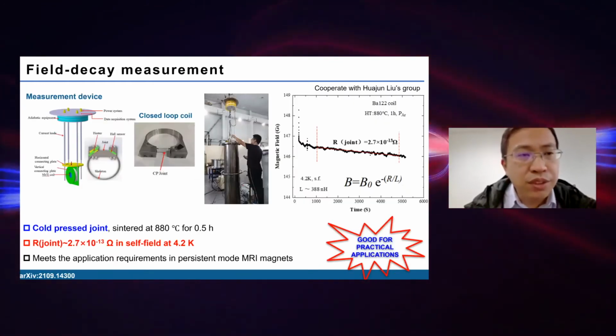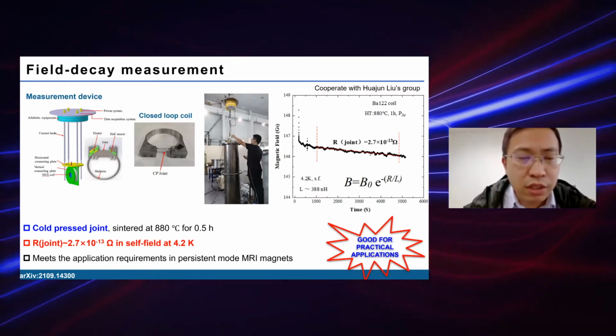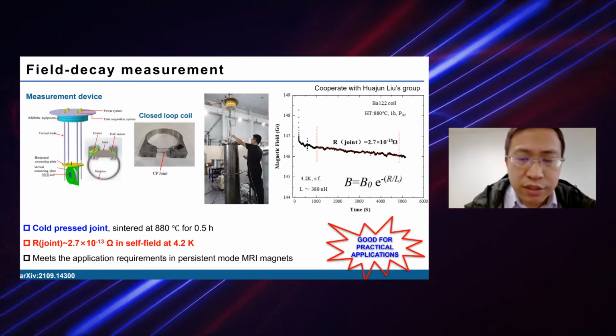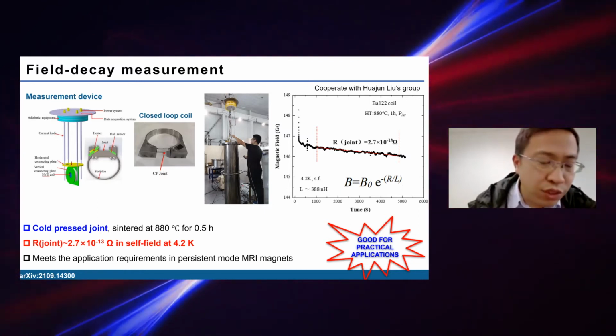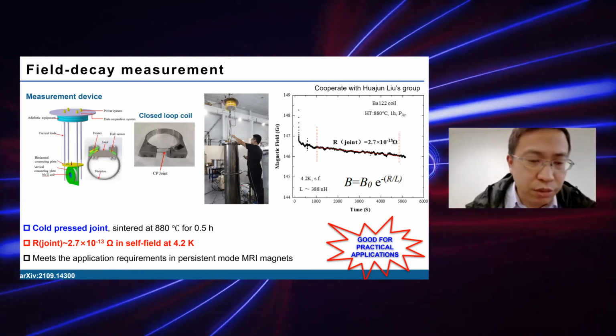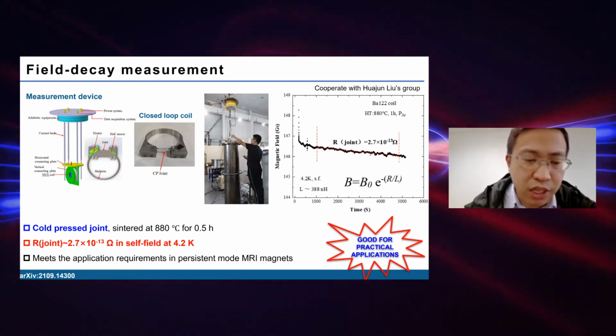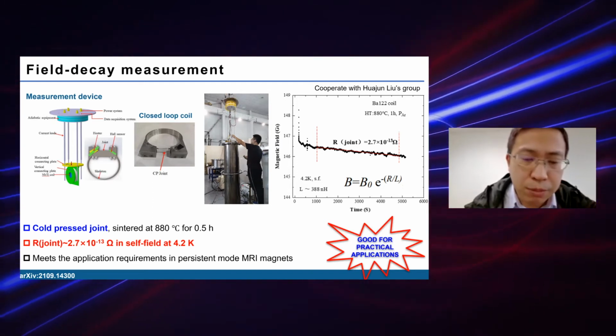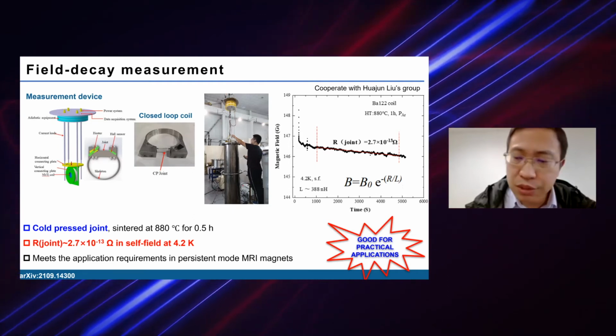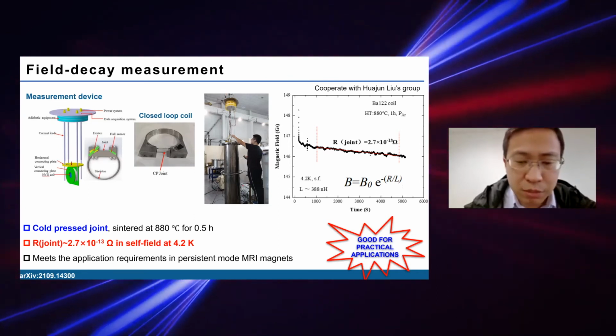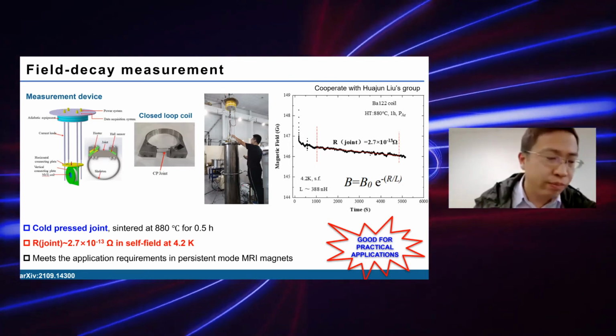And by using the field decay measurement, we can see that the joint resistance is decreased to 10^-13 ohm at self field and 4.2 Kelvin. It's very good news for persistent mode MRI magnets.